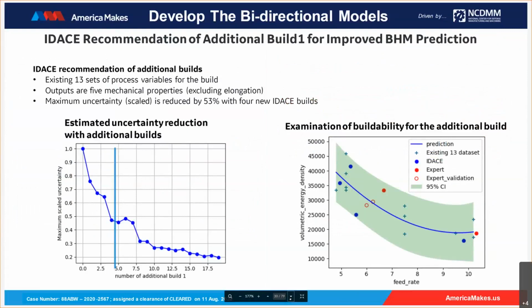Then, after screening out the domain that is more likely to be buildable, we performed IDACE to identify the few points with estimated uncertainty reduction, as shown in the left figure. The horizontal axis is the number of recommended builds. The vertical axis is the estimated uncertainty. As you can see, with a few points, like 5 points recommended from IDACE, the estimated uncertainty could be reduced by 50%. That also means our BHM model could be improved by 50% over the current one with 5 additional walls. So using this estimated uncertainty, we recommended 5 walls to be built for model refinement, and we also examined that the buildability constraint is strictly satisfied, and we also visualized the pairwise plot. And next slide, Neil, please.